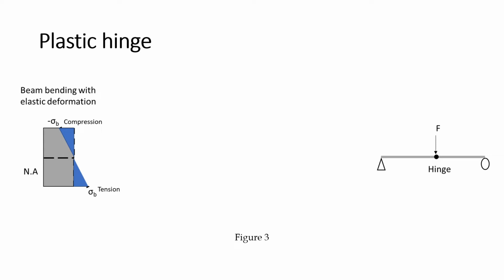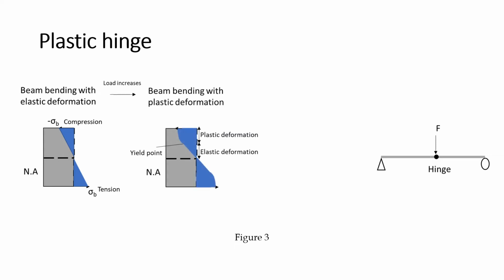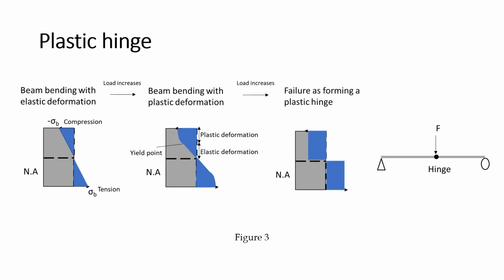This shape of the stress distribution over the cross-section is assumed for using equation 1 to calculate the bending stress. Later, when the load increases and the beam starts to be plastically deformed, materials close to top and bottom faces start to yield. This makes the shape of the stress distribution deviate from its original shape, making equation 1 overestimate the actual stress value. Eventually, when the load gets high enough to make all the materials over the cross-section yield, the entire cross-section starts to lose its stiffness and behaves like a hinge.